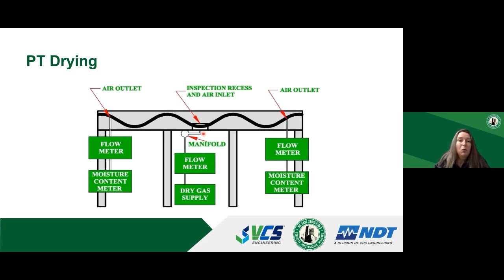Then there can be one or two outports that are connected to a flow meter that is also connected to a moisture meter that is recording the relative humidity and the temperature coming out. The dry gas that is supplied through the inport pushes the air inside the tendon through the outports, and this process continues until the air inside the duct is dried out to below that threshold line that separates the dry tendons from the moist tendons.